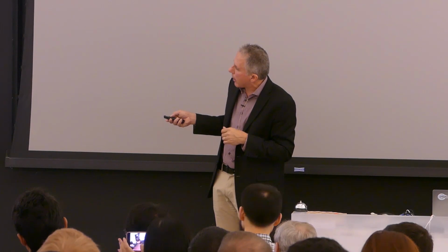So I'll just mention here one example of an exciting result for catalytic selectivity. This is from my colleagues Jonas Peters and Theo Agapie, who showed that molecular catalyst pyridines, in this case nitrogen functionalized aryl pyridinium, which initially start out as molecular catalysts in the electrolyte, condense and form an electrochemically deposited film on a cathode, which can now generate dicarbon products, ethylene, ethanol and propanol, at a fraction relative to the total reduced products of carbon of more than 80%, reduces hydrogen evolution to a few percent, and reduces the fraction of methane generated relative to C2 products by more than 2 orders of magnitude. So this is an example of the kinds of things that are possible.